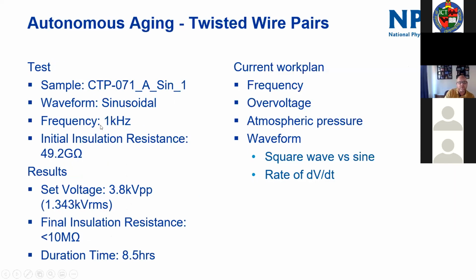We then aged that sample. In this case, we aged it with a sinusoidal waveform at 1 kilohertz frequency. We set the voltage to 3.8 kilovolts peak to peak, which is slightly above the inception voltage, just so we got continuous PD discharge. And the insulation on those twisted wire pairs broke down to less than 10 megaohms in about 8.5 hours at 1000 hertz. And we're continuing this work at the moment.